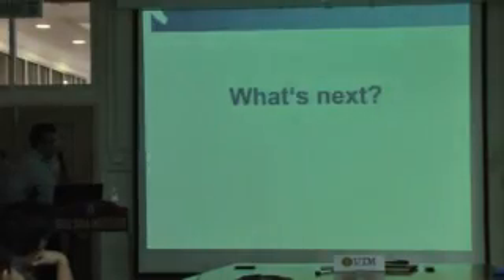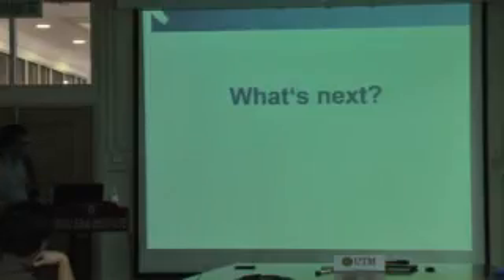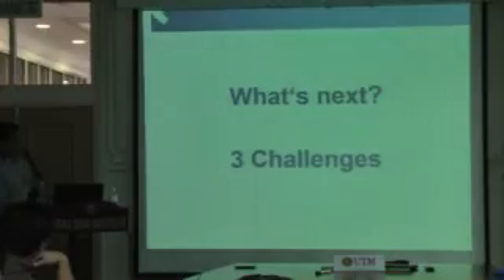So basically the question is what's next. We get 8.1%, it's not good enough. If you want to talk about market application, you need to start talking about 15, 20%, or even 25%, some say, then we can really start talking about it. So I will try to tackle this in the next half of my talk by showing you three challenges that the field is having. The first one is rather obvious. Taking bismuth vanadate for example, it's now really limited by the band gap. 2.4 electron volts limits it to 7.5 milliamps, so you can't go further.